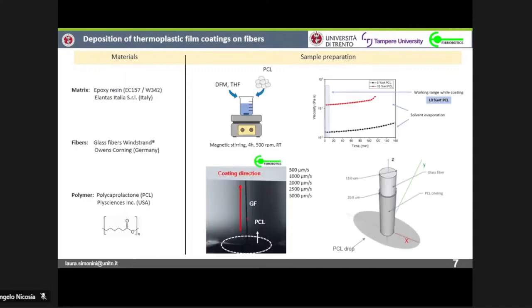We dissolved PCL in DMF and THF to obtain a liquid solution of PCL, and then using this particular device that was developed by Fibrobotics in Finland, we take just one drop of this liquid PCL and we force one single fiber to pass through the liquid PCL in one direction with different coating speeds. So the idea is the one schematized here: we want to obtain a coating like this, a sort of sizing.